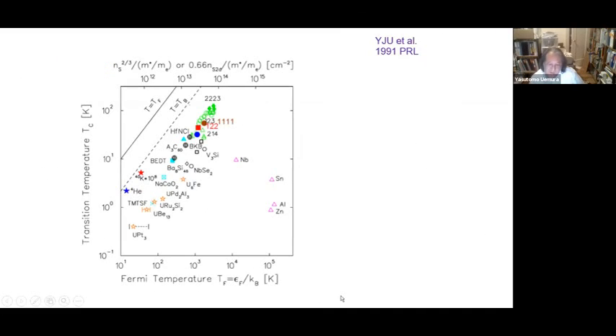Okay, so then we made this a little bit more quantitative by obtaining an energy scale, which I call the effective Fermi temperature, by using the number density of carriers and mass we estimated from superfluid density. And so this is a plot of that. And these are cuprates and buckyballs, the unconventional superconductors. They have very high Tc with respect to this effective Fermi temperature or Drude spectral weight temperature. And the linear line I showed corresponds to this line, but as compared to that, the BCS superconductors have very high Fermi temperature, but rather small Tc.